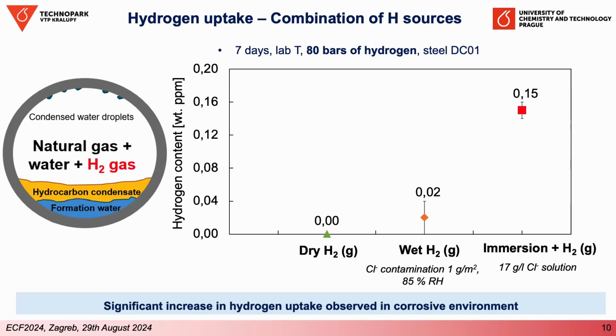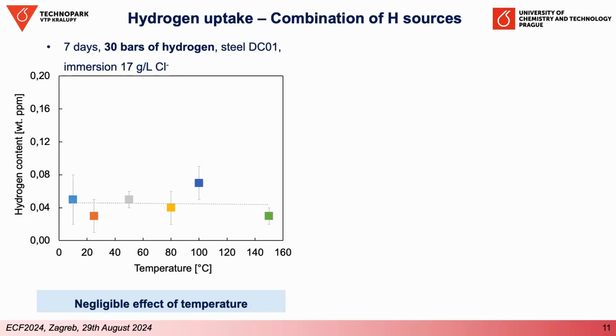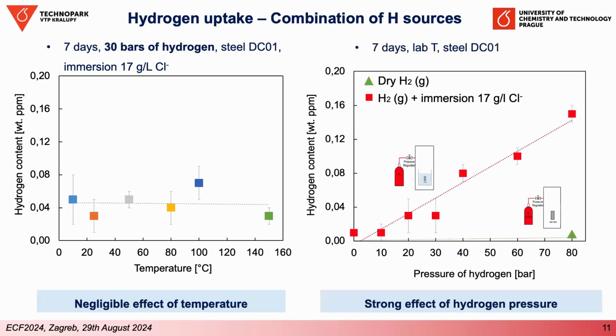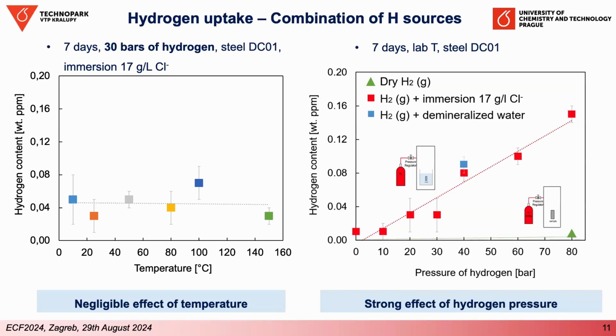what the factors are that drive this promoting effect. So we did some more testing with a focus on temperature. We saw that there is a negligible effect of temperature on this promoting effect, but it's clearly driven by the pressure of hydrogen. But still, we are working on it with the effort to understand the mechanism behind it. It works also with demineralized water.